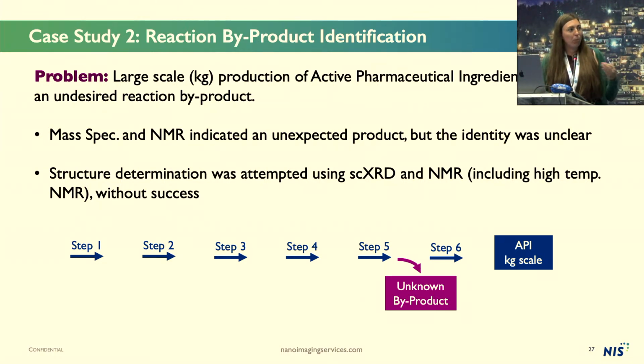They went through quite a lot of steps to try to determine this structure. They tried single crystal X-ray diffraction. They couldn't get big enough crystals. They did a lot of sophisticated NMR experiments. They sent it to a CRO to perform some fancy high-temp NMR experiments, and none of this was successful. They just couldn't quite figure out what had gone on here.